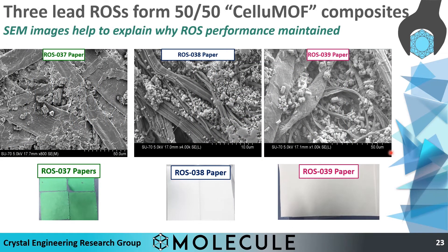A couple of other interesting outcomes to the Aquasorb project: first, all four of the ROS materials that ended up being the winners are relatively dense, which is not the case for most benchmark materials reported in the literature. Second, in studying various composites — polymer composites and cellulose composites — we found that 50/50 cellulose composites offer optimal performance because the cellulose is an excellent matrix to expose the full surface area of the MOF or ROS particles. Other composites involving polymers significantly reduced the performance of the sorbent, but cellulose composites retained it.